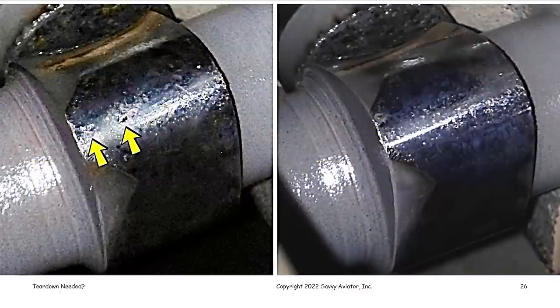So here are two Continental cam lobes. The one on the left, those arrows are pointing to things that clearly are crack-like features on the apex of the cam lobe. And the cam lobe is coming apart, and that cam is unairworthy. The right-hand picture has a cam with, you know, typical wear. It's got some pitting on the toe of the cam lobe, but not anything significant. And the important thing to understand about these cams is